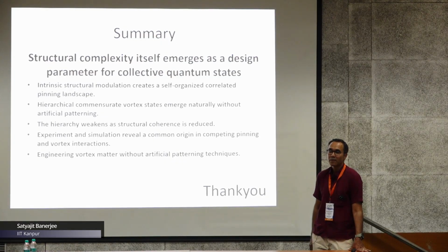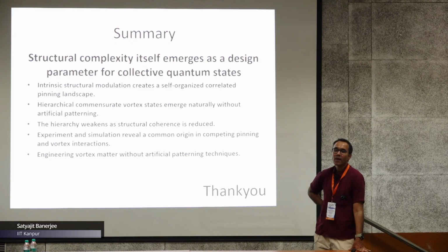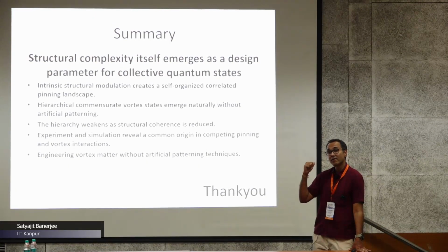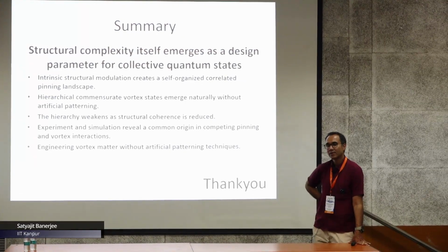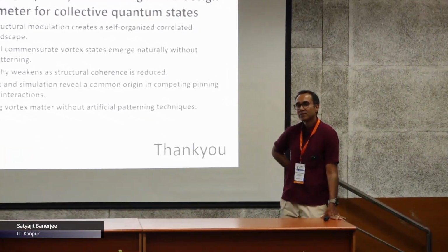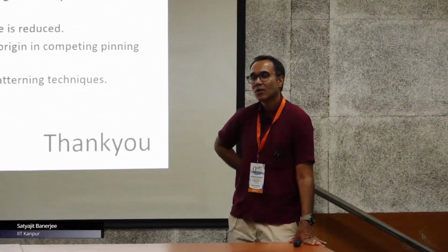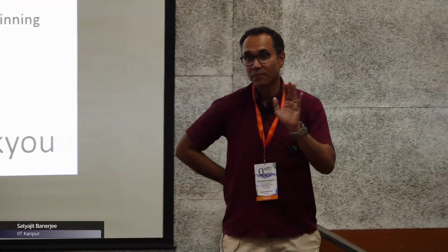So basically, here you are changing the annealing parameter, like at what temperature, for sample Y? Then you get the periodic pinning potential, right? No, not for sample X. For sample X, these are as-grown crystals, but of course they are grown in a particular condition.